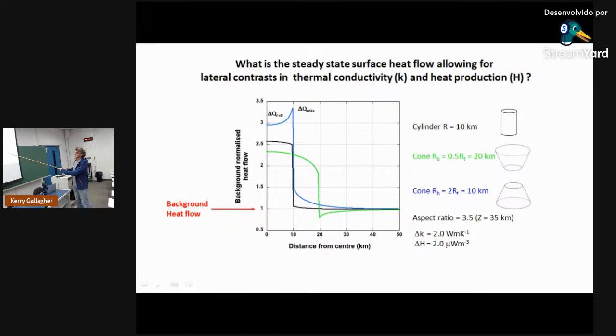Okay, so what we see over the top of the granite, in all cases, we get enhanced heat flow because of the heat production. The case like this, here, the blue, we see this sort of peak heat flow at the edge, because what happens there is, heat's trying to come up vertically, but it gets focused into this cone because of the thermal conductivity, so it has a higher thermal conductivity. So it sort of acts like a pipe that the heat gets concentrated and comes up to the surface. And the biggest effect is actually on the edge, as we see here.